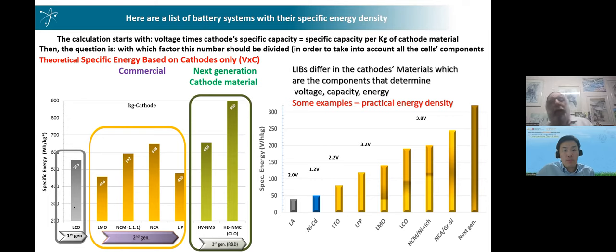But then the question is, by what factor we have to divide this initial number in order to take into account the negative electrodes, the electrolyte solution, the case, and all the current collectors, etc. In good cases, we can start with multiplying voltage times capacity, and then the factor is something between 2 to 3. And of course, we want to minimize the factor by which we have to divide the initial number of voltage times capacity of the cathode material. So now let's go to the examples.